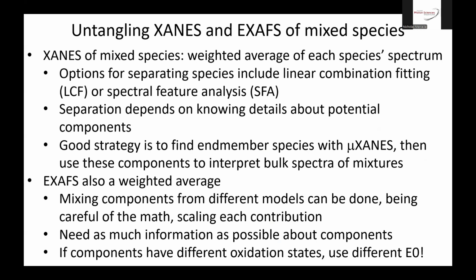Okay, so the last thing I want to talk about is how to untangle spectra that are mixtures of species. So XANES of mixed species are basically a weighted average of each species spectrum within the beam's footprint. And so options for separating those out include linear combination fitting or spectral feature analysis. I'll describe them on the next slide. But the separation depends on knowing the details about the potential components. If you don't know anything about the components that are there, you don't know what the mix is.